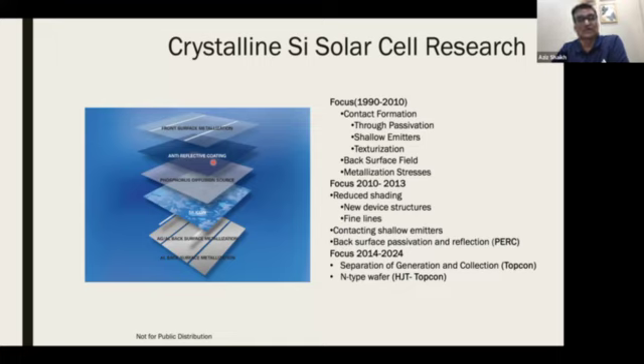You also have a texturization of the surface, which traps the light. And then you have a collection grid, where you would collect the charge carriers. On the back side, in this scheme, this is a simplistic scheme, you have this back surface field metallization, which is aluminum. So this is about 3 generation back technology, but it gives you some fundamentals.